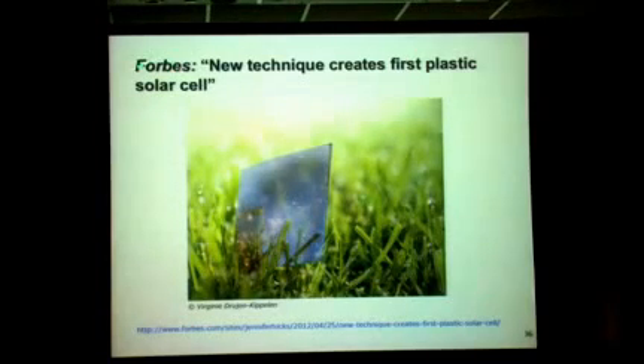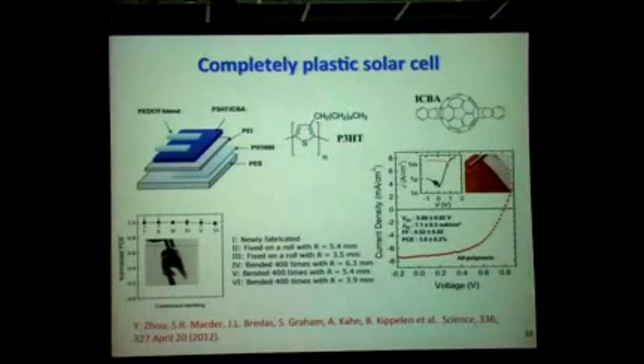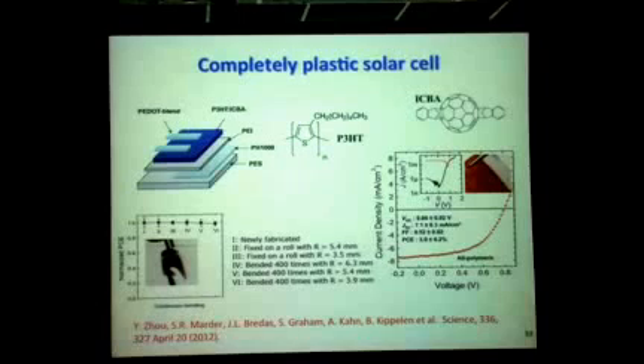If you want to read them, there's actually an article on Forbes.com about them. And what's nice about these polymeric solar cells is they really have truly unique mechanical properties. You can bend them down to a bending radius of just a few millimeters, and it's very stable. Again, this is in materials that require much less packaging, and you still have to protect the active layers somehow, but it's a completely different story because you don't have lithium fluoride or calcium in your device structure anymore.